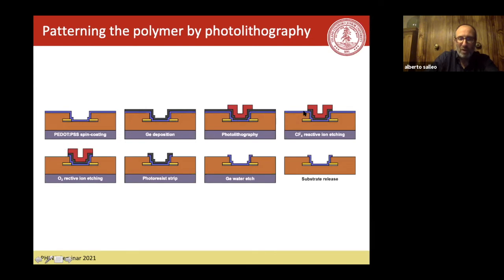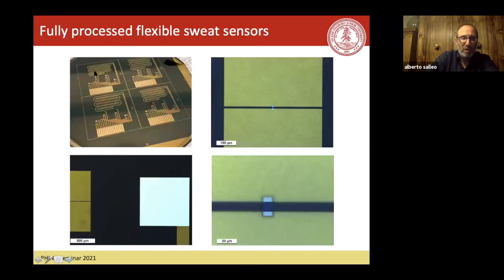So the germanium etch is one chemistry. It's carbon tetrafluoride. The polymer etch is a different chemistry. It's oxygen, so you just essentially ash it away. Then you remove the photoresist, you strip it, which would destroy the polymer, but the polymer is protected by the germanium, so the polymer survives. And then you strip the germanium with water, and now you're left with your device. So this looks pretty simple. It's 2 slides, but this took several months to develop. And eventually we were able to make these chips.